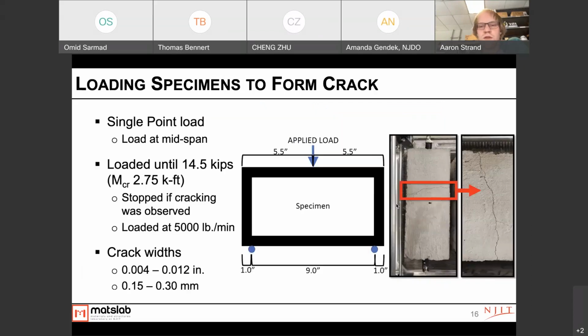In order to form the crack inside the specimens, we applied a single point load, with the specimens turned upside down so the surface was on the bottom. They were loaded up to 14.5 kips, though the test was stopped if cracking was observed. This was done at 5,000 pounds per minute. Through this method, we didn't actually control the crack width, but we did measure them, and they resulted in crack widths between 0.004 and 0.012 inches. The cracked specimens were randomly assigned brine levels to minimize any bias, such as a small crack on a low brine and a large crack on a high brine, or vice versa.